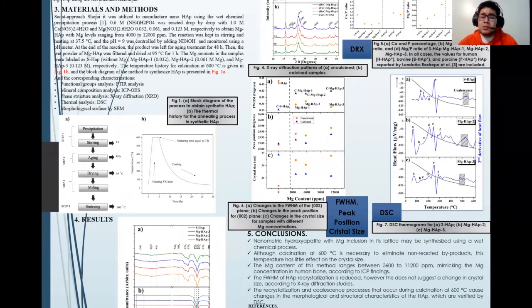I follow the method published by Shohei because it's simple and easy to reproduce. I use ammonium phosphate 0.6 molar as phosphorus precursor, calcium nitrate 1 molar as calcium precursor, and magnesium nitrate as magnesium precursor, at 0.032, 0.061, and 0.123 molar, respectively, to synthesize all the samples.